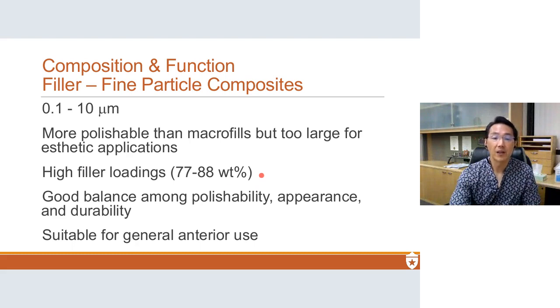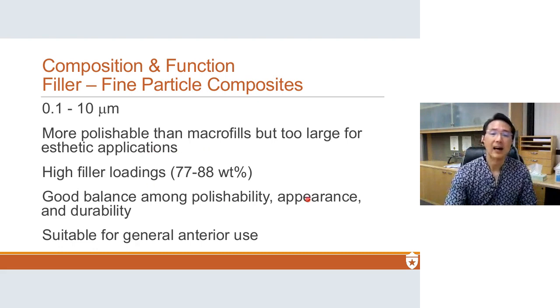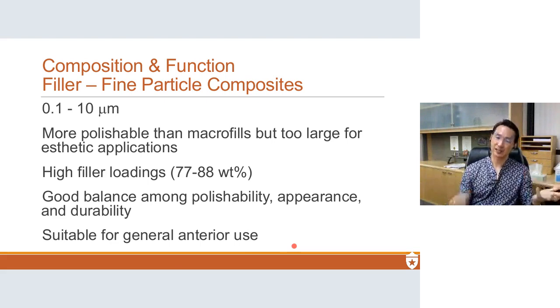The filler loadings were pretty good. Again, this is weight percent. The filler particles are more dense than the resin, so don't get tricked by that. Companies love to use weight percent because it's easy to measure, but it's a higher number than volume percent. So it makes their product look better. And so they had a good balance between polishability and durability. And they were kind of suitable for general anterior use, but they weren't the strongest and they weren't the prettiest, okay?